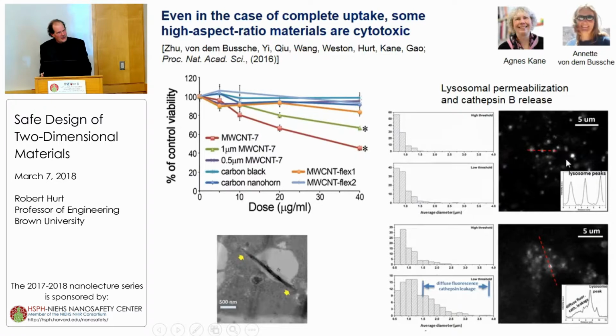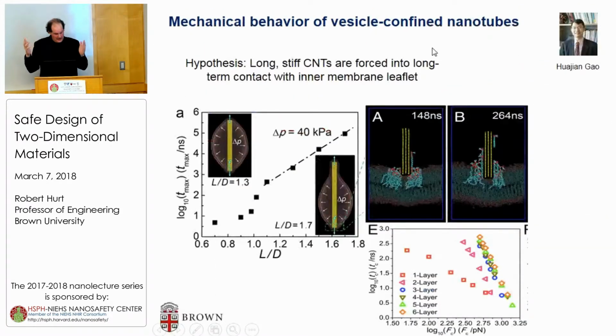And this data shows that in an unexposed cell, this cathepsin B remains intact inside all these point-like lysosomes. But in the case of nanotube exposure, you still see the lysosomes, at least most of them, but you see this diffuse glow around them that shows the release of cathepsin B into the cytosol in the near lysosomal region. So this has to do with lysosomal damage, we believe.